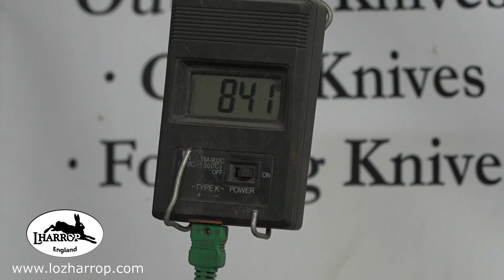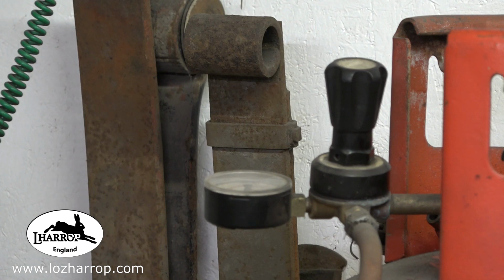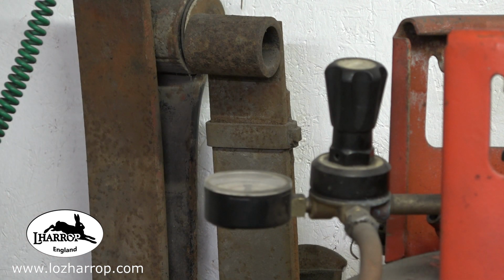So this is just showing the readout on the thermocouple in the heat treat oven. And this is a gas oven. I've got 2, an electric and a gas. It's very, very accurate, this gas oven. It's a great little oven. It only takes about 5 minutes to get up to temperature, and it's very, very controllable. You can't really walk away and leave it. You do have to monitor it, and the temperature is controlled by that valve there, which is very, very micro adjustable, so I can set any given temperature.